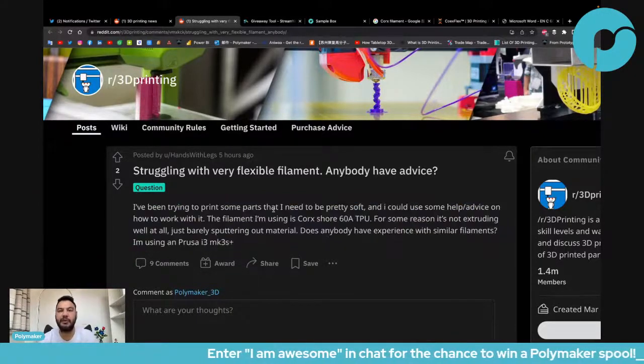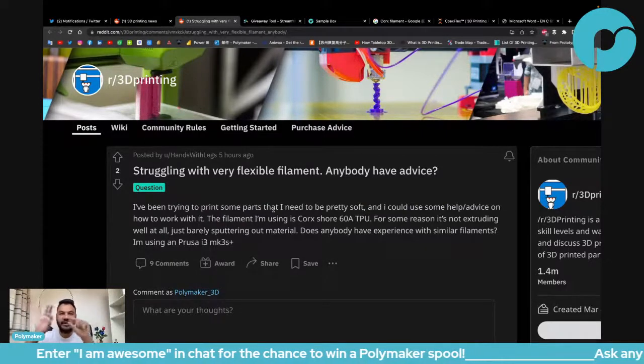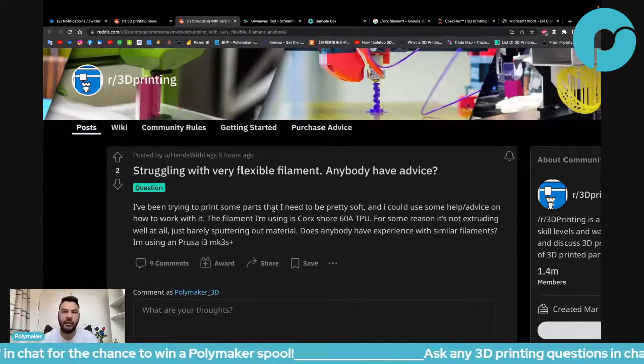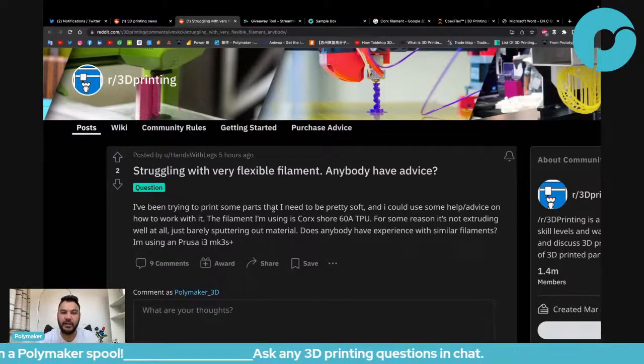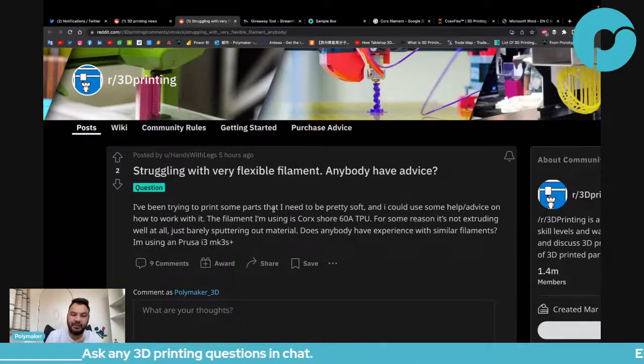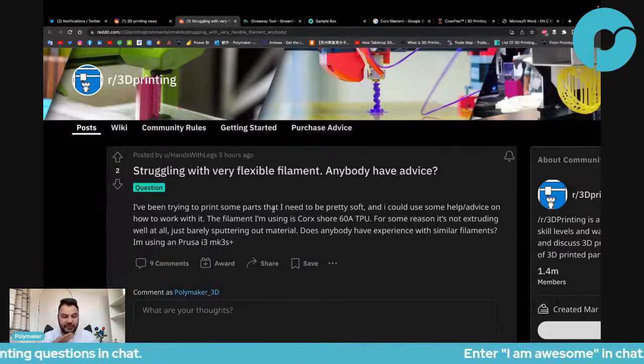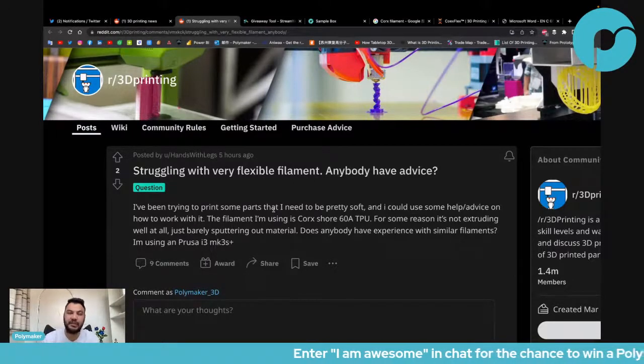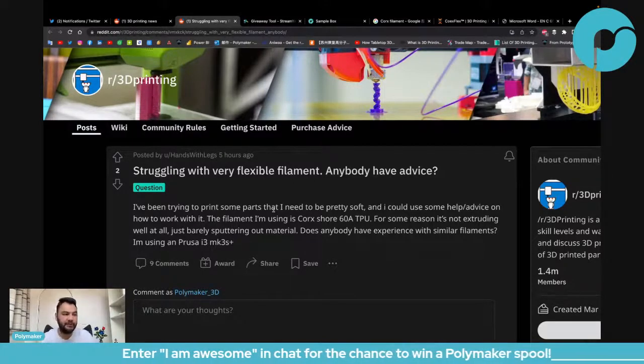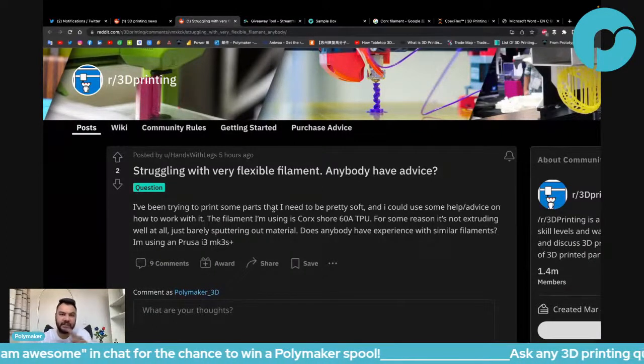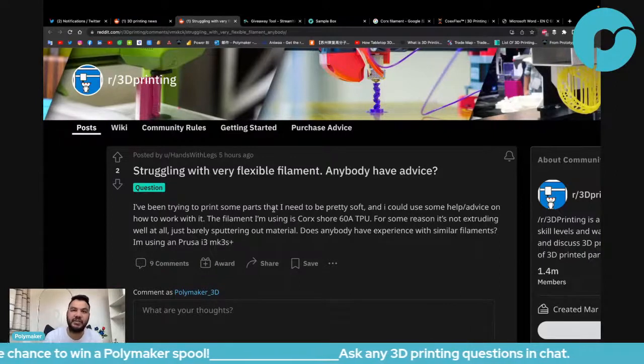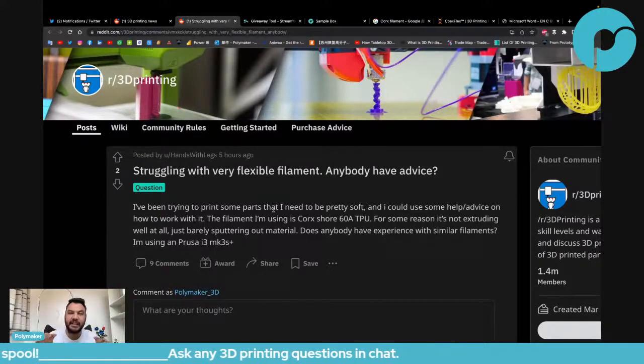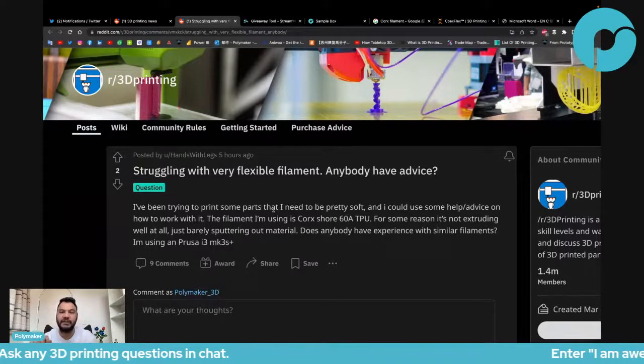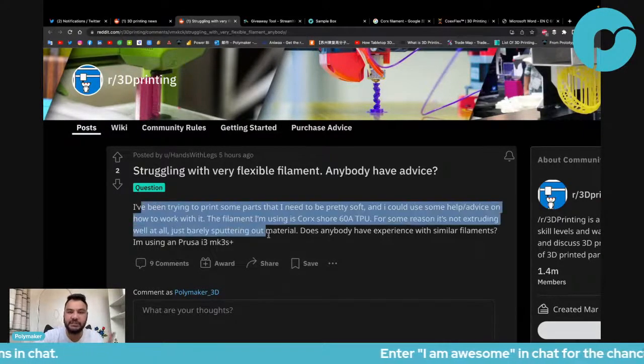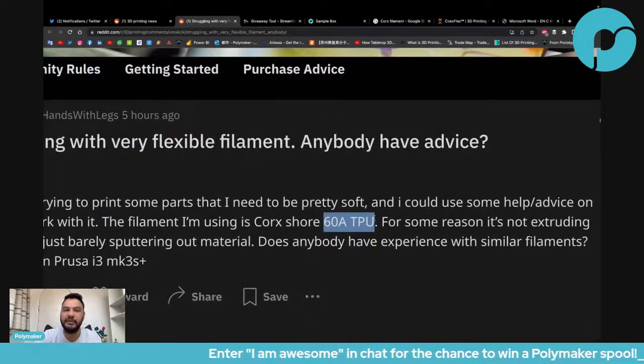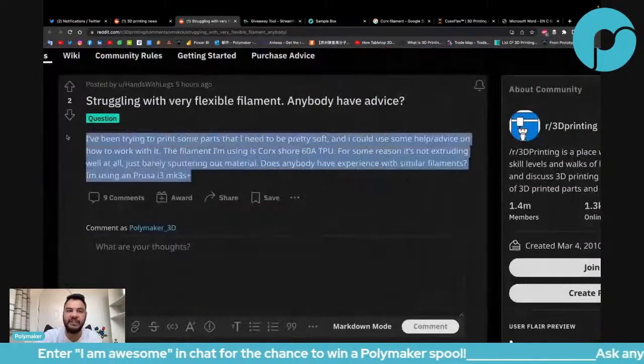So, for example, we had a lot of customers that are doing insoles, right? Insoles for your shoes and also the upper shoe, and even though the insole needs different flexibility, what they do is they have different profiles, but they use the same material. They use 95A for all the different insoles. Even if you have soft insole, hard insole, and semi-hard insole, they all use exactly the same material, but the infill inside is customized, and that's how it makes the different softness. So that's for me the first mistake: to use a basically unprintable material just because you need something soft.